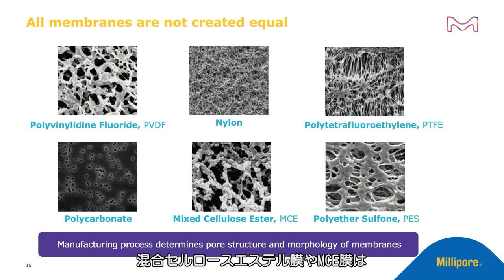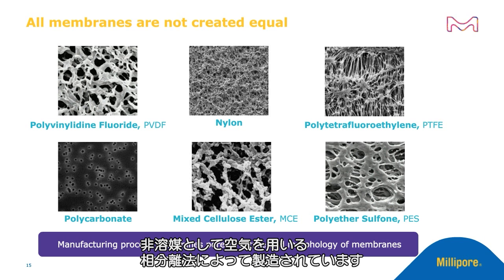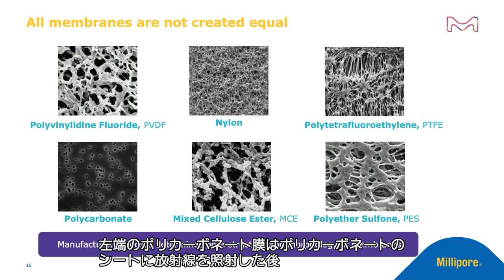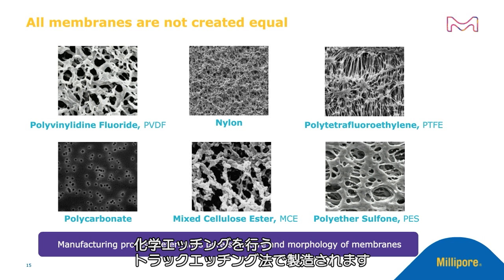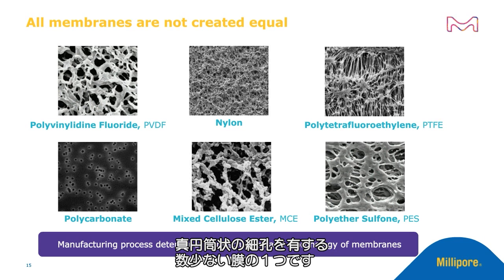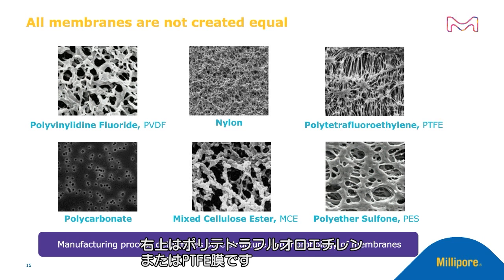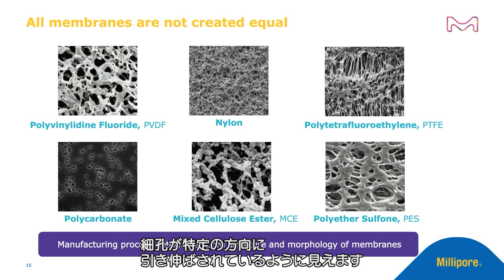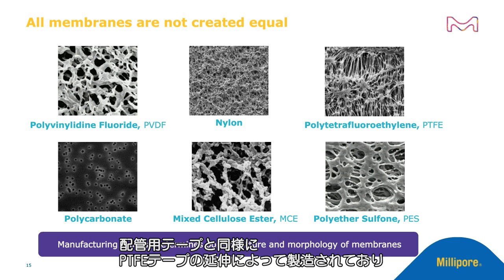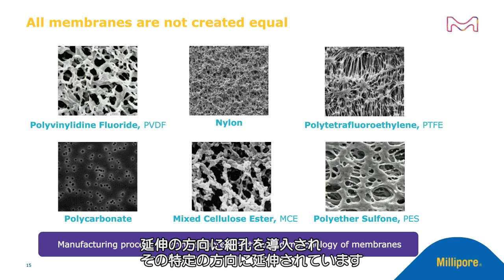A mixed cellulose ester or MCE membrane is also manufactured by a phase separation method where air is used as a non-solvent. The polycarbonate membrane presented at the left-hand corner is manufactured by a track etching process, whereby a sheet of polycarbonate is irradiated followed by chemical etching. This is one of the very few membranes which have truly cylindrical pores. On the top right-hand side, we have the polytetrafluoroethylene or PTFE membrane, where the pores look stretched in one particular dimension. And that is because this particular membrane is made by stretching a PTFE tape similar to a plumber's tape. And the direction of stretch will introduce the pores, and they are elongated in that certain direction.